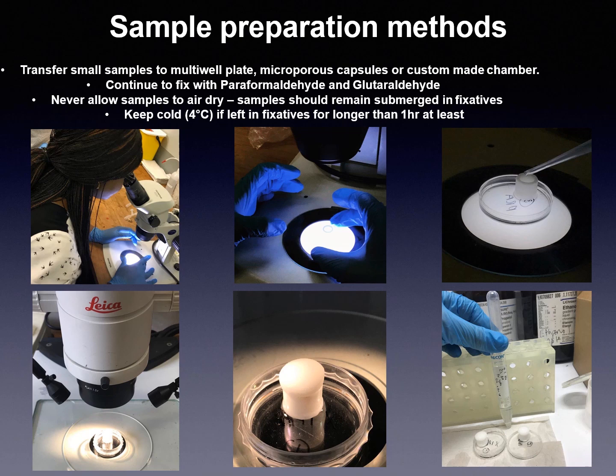Sample preparation methods. There are different methods of preparing the sample. The sample can be transferred into a small multi-well plate, microporous capsules, or a custom-made chamber. Continue to fix with paraformaldehyde and glutaraldehyde. Never allow a sample to air dry. Samples should remain submerged in fixative, kept cold at 4 degrees, and left in fixative for longer than an hour.